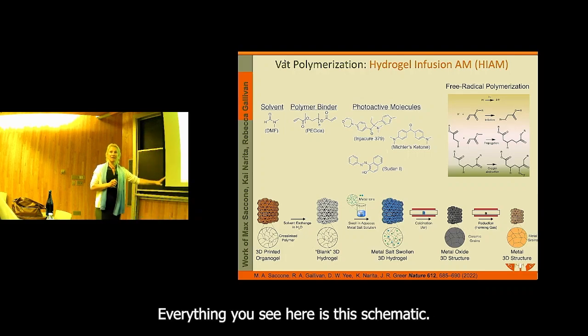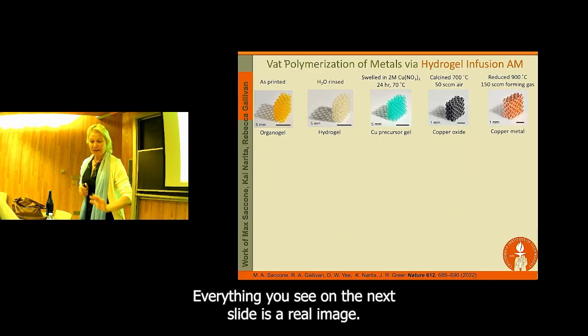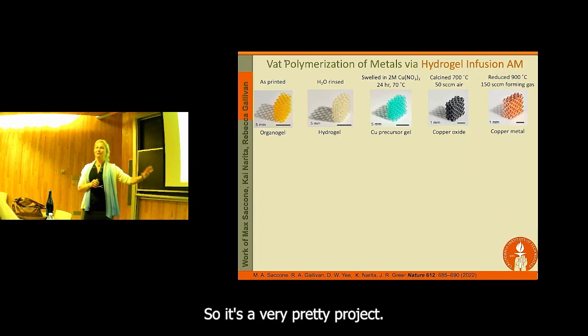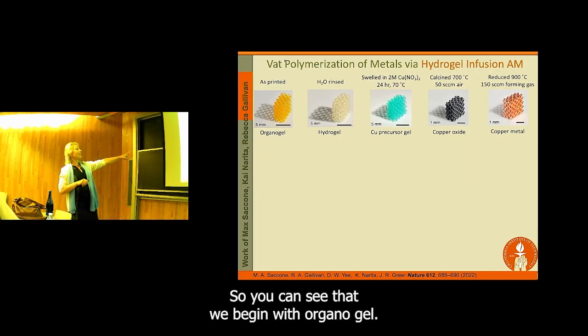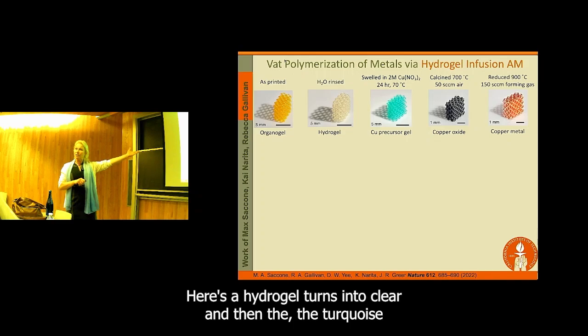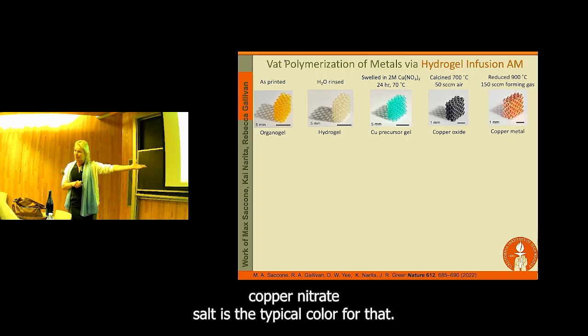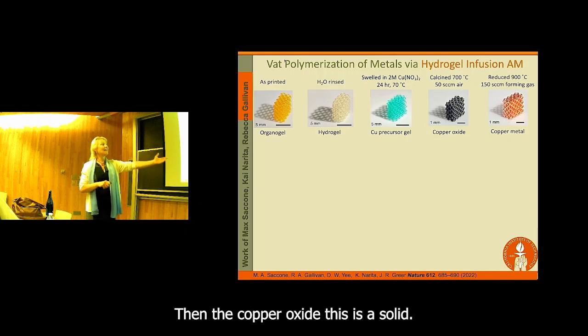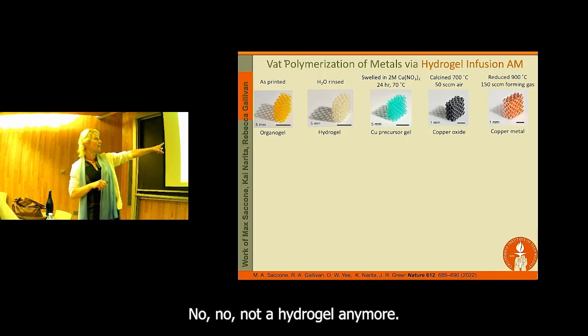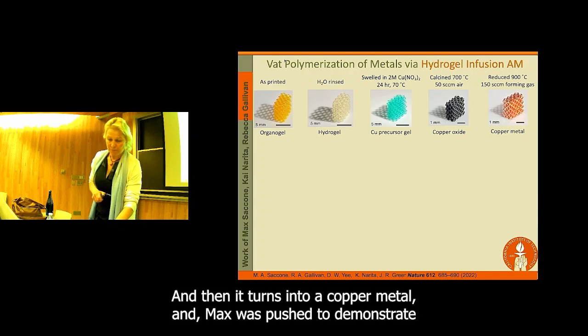Everything you see here is a schematic, okay? Everything you see on the next slide is a real image. So it's a very pretty project. So you can see that we begin with organogel. Here's a hydrogel, turns into clear. And then the turquoise copper nitrate salt is the typical color for that. Then the copper oxide, this is a solid now, not a hydrogel anymore. This is a rigid solid copper oxide, and then it turns into a copper metal.